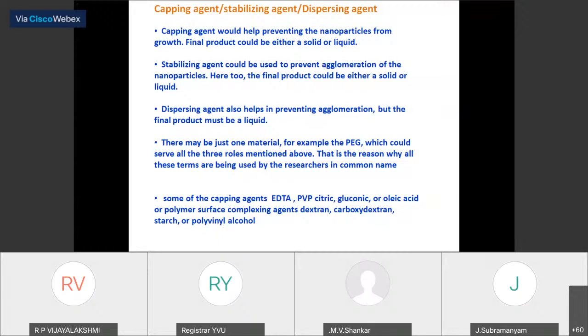So to control the growth of a particular particle while growing, we have to use the capping agent, stabilizing agent, and the dispersing agent. The dispersing agent is used to improve solubility. We have the capping agent and the stabilizing agent. These two terms are used side by side. How the capping agent works: as soon as the nucleation starts, we have the growth. As soon as the growth starts, we have to control the size of the particle. So we have to avoid the growth in all directions.